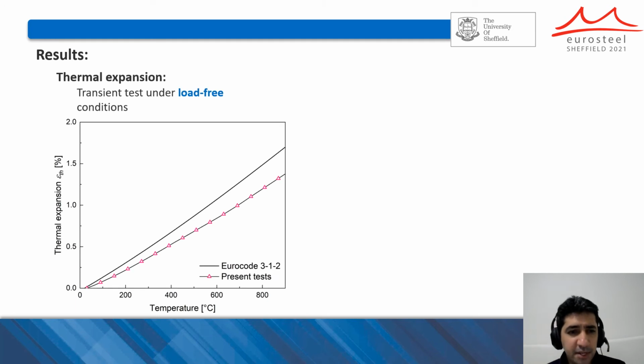Results. As previously mentioned, the thermal expansion of the material can be obtained if a transient test is performed under load-free conditions. In this figure, you can see the results of the present study for thermal expansion in comparison with the diagram presented in Annex C of Eurocode 3 Part 1-2. As you can see, Eurocode significantly overestimates the thermal expansion of grade 304 stainless steel plates. It is on the safe side, but there is a kind of overestimation in Eurocode.